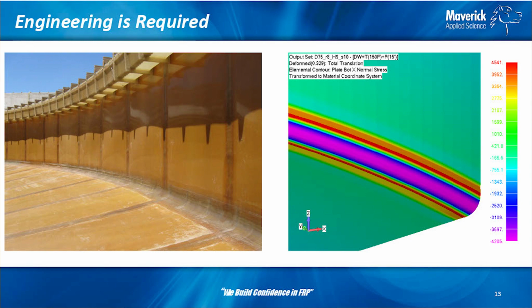So here's a closer look at this lining. These were the same linings that Kevin showed earlier. This was in Baja, California, so very south, very tropic. Our inspector was here for about 3 years looking over these projects, so really good inspector. He definitely liked this climate. But he would take temperatures on this at midday, and he would see 140, 150, and all of a sudden, with no pressure, these were expanding such that they were buckling and moving.